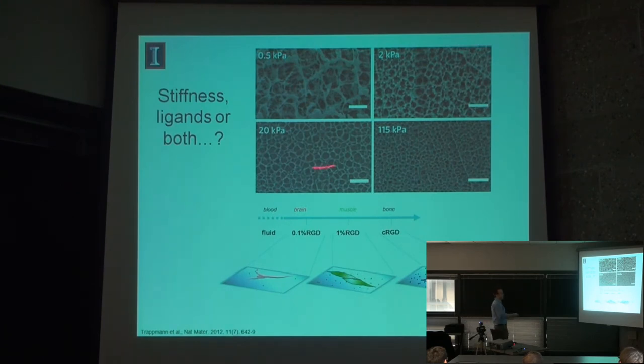And I think this has been in my mind and others' for a long time, that when you cross-link polyacrylamide, which is the gel they used in this study, and you vary cross-linking density, you're not just varying stiffness, you're varying the porosity. And so this is an SEM image of soft gels and stiff gels across a range of mechanical properties. And so you get very different pore sizes in these materials. And if you're cross-linking your protein that the cells are going to grab onto at the surface, I mean, look at what the cell's going to see.